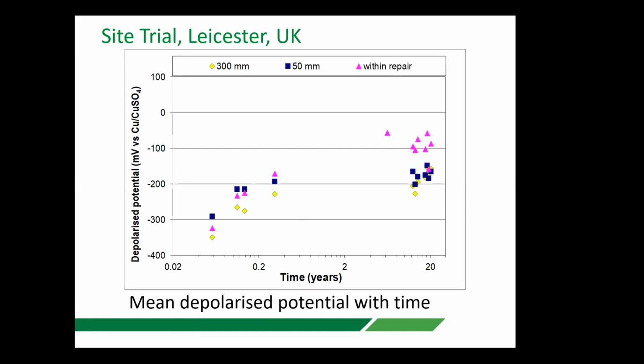Looking at the depolarized potentials, i.e., once we've turned off the current and then looked at the potentials of the steel reinforcement 24 hours later, we could see that with time, the potentials moved in a positive direction, and therefore became passive. Anything above -200 versus copper sulfate is normally considered to be passive. There's a slight issue there, which I'll talk about a little bit later.